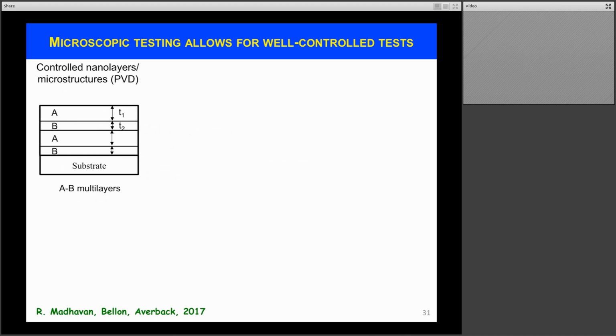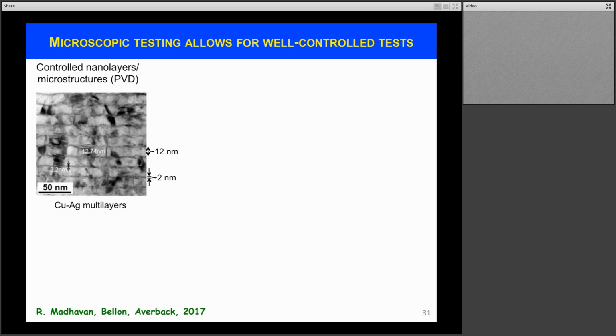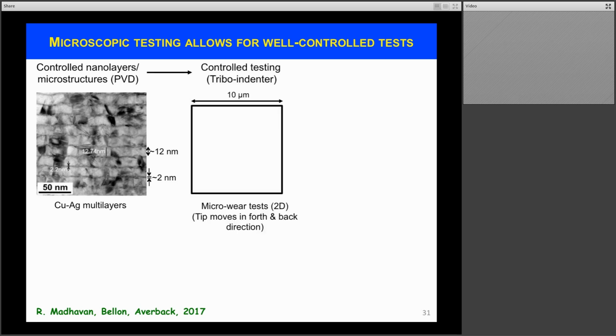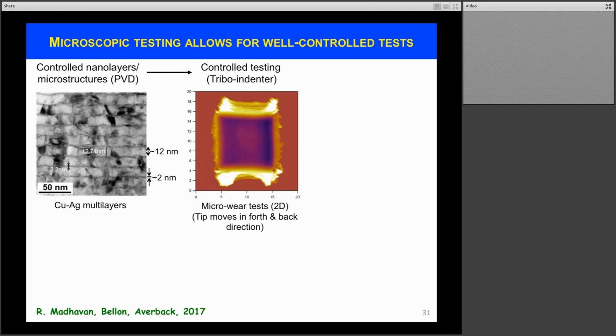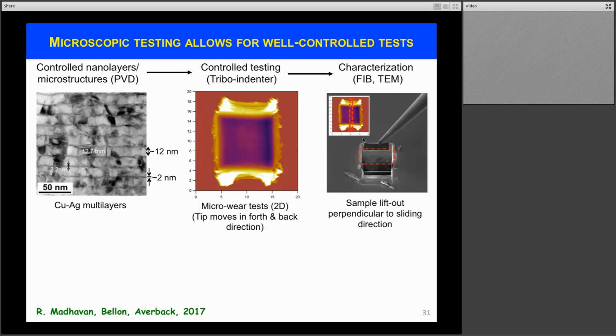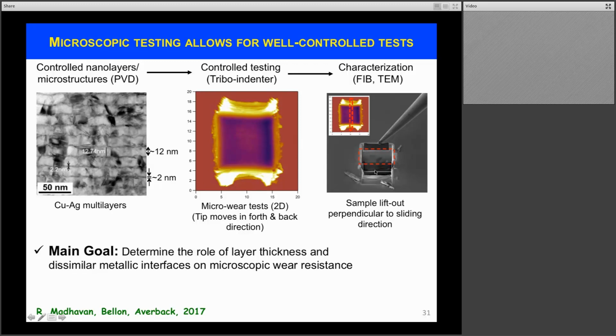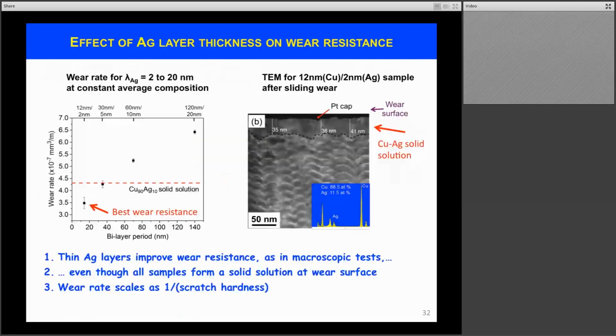So instead of letting a system develop multilayers, we would grow multilayers by physical vapor deposition. Here you see your copper-silver multilayer. Then we use a tribo indenter to scratch a patch on the surface of these multilayers. We can image this by AFM to measure the wear rate, and also use FIB and TEM to observe the microstructure just below this wear surface. The main goal is to determine the role of layer thickness on wear resistance here at the microscopic scale.